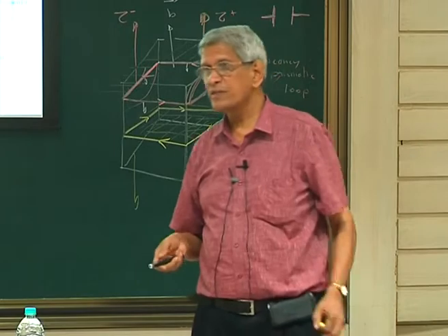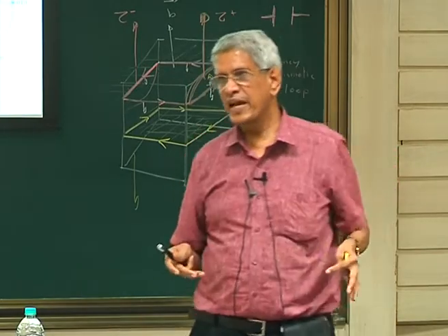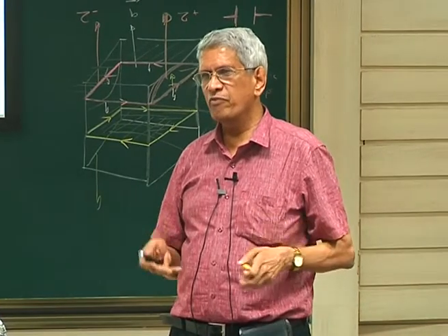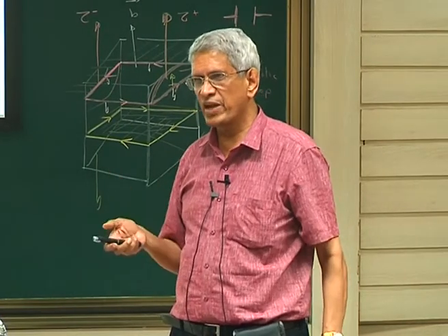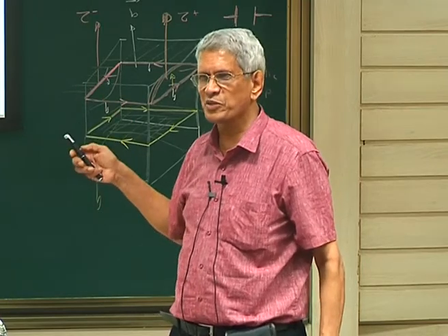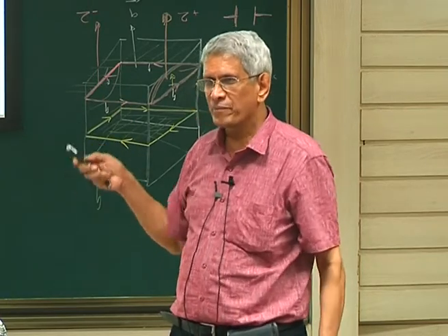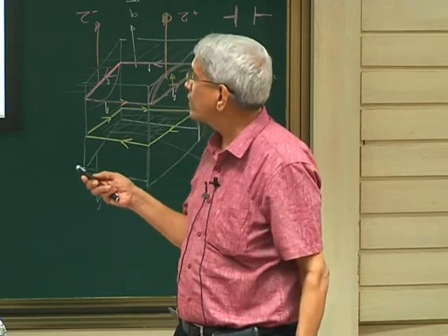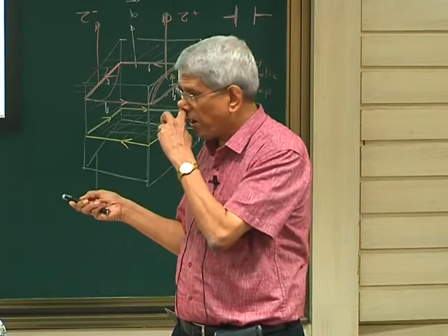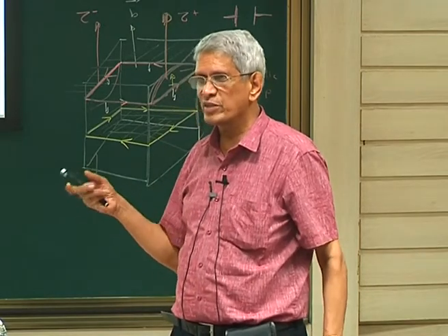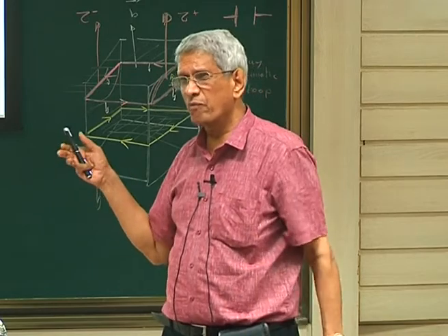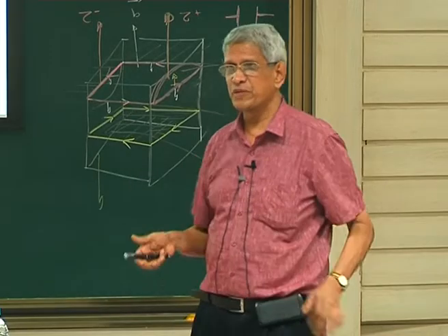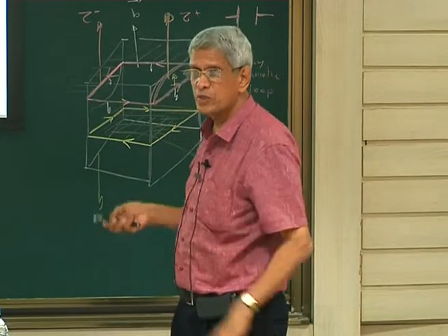But in a reciprocal lattice, what we do is that we consider a lattice. We don't consider atom positions in that consideration. But when we consider real materials and we consider diffraction, we consider the intensity corresponding to it. And the finite size of the sample we will consider, because of which we can have the spot size, streaking, and all those things will depend upon the type of material and the type of sample size which we consider. But otherwise this is the reciprocal lattice.